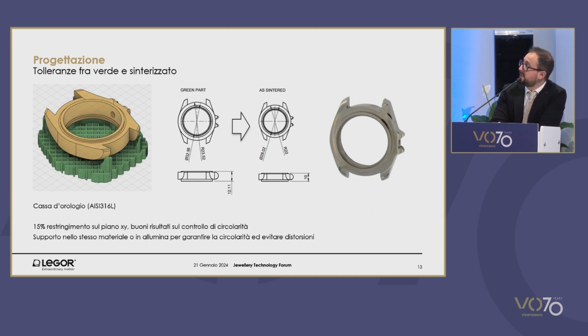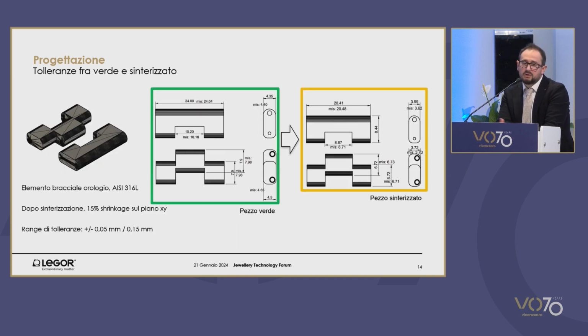On your left in green, you can see another support. This is for a watch box. This is AISI 316L. And in this way, we can guarantee excellent tolerance in terms of the circular shape of the item. The very same item produced without the support showed a distortion with a tapering between the base and the upper part of the object. This is another example. Here you can see the different tolerances. We're talking about items with a base size less than 8 times 8 centimeters and 7 centimeters in height. Possible tolerance range goes from 0.05 to 0.15 millimeters, depending on the geometry of the item and depending on all the other aspects.